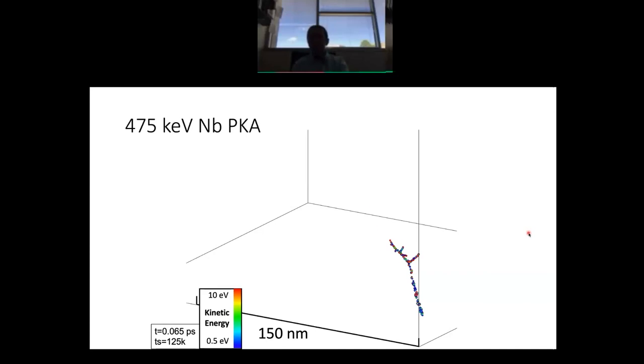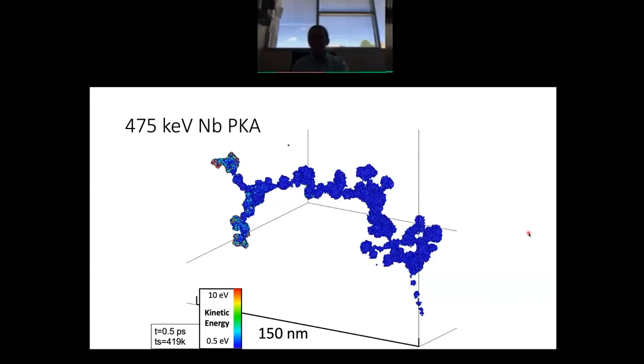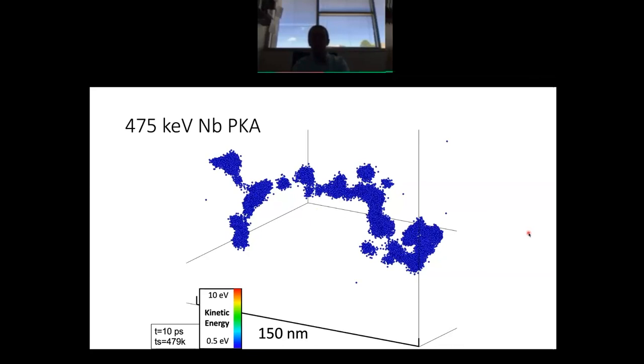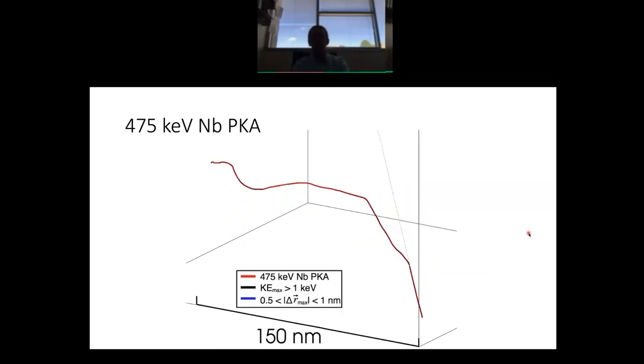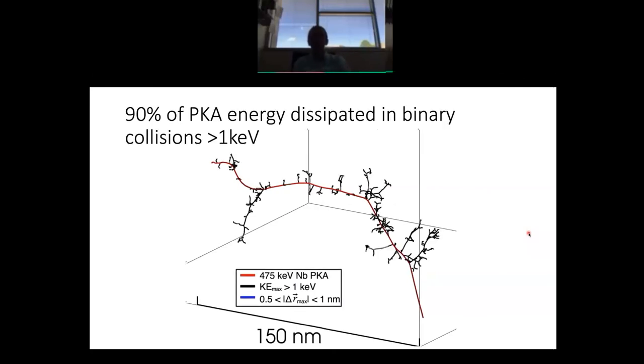So it starts out like this, and then it continues to propagate out, and you get this full-blown collision cascade developing inside the material. Because all of these structures were actually recorded, we could then go back and analyze exactly what happened. So this is the flight path of that primary knock-on atom. Coming off of that flight path are a bunch of secondary knock-on atoms.